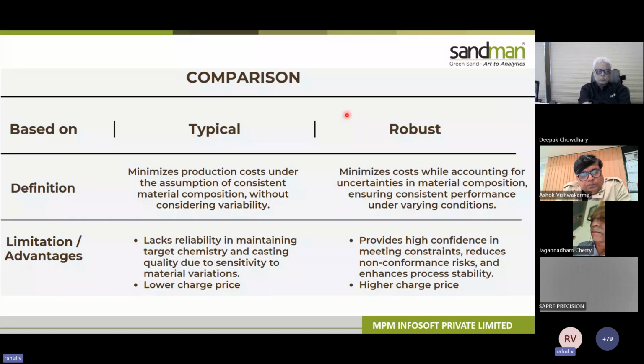So the comparison between the typical and the robust formulation is as follows. The typical formulation works well as long as there is no uncertainty in the material composition. Once uncertainty happens, there is a very high chance that we will fall out of the target chemistry. But the robust charge mix will handle these cases. The thing is that this formulation will give a cost which is a little bit more expensive compared to the typical formulation. Still, we'll be able to get our chemistry well within the target specification.